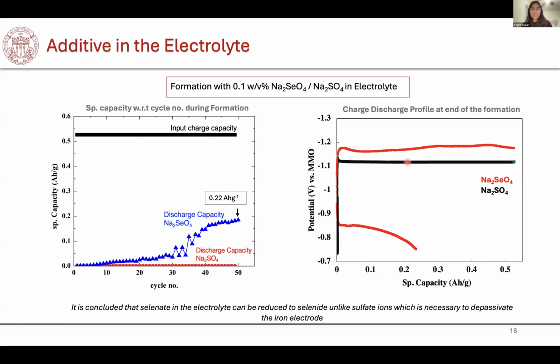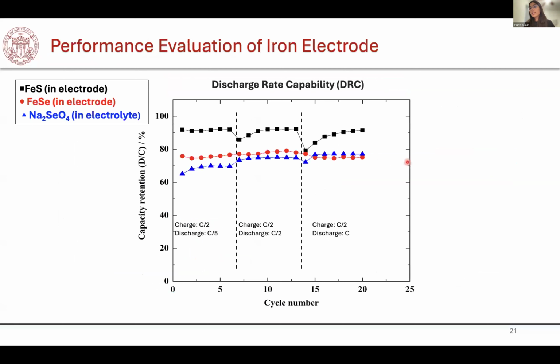And moving on, so now we have introduced the additive through the electrode and the electrolyte. The next thing was to study their discharge rate capabilities. To do that, I charged the electrode at a constant rate of C/2 and then discharged at different rates from C/5 to 1C rate.